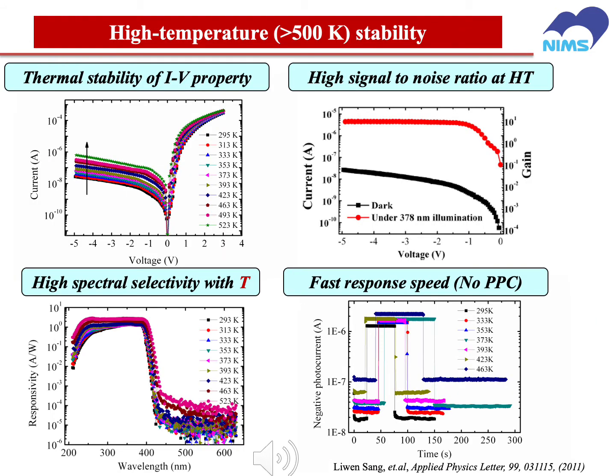And we also found that the device shows a very good high temperature stability, and this is the thermal stability of the dark current. It shows a little increase with the temperature increasing, but still is very low, lower than 10 to the -6 when the temperature is higher than 500 Kelvin. And the signal to noise ratio is also very good at high temperature. And the spectral selectivity also did not degrade when the temperature is increasing. The response speed is also very good, and without the PPC observed even at the temperature higher than 463 Kelvin.